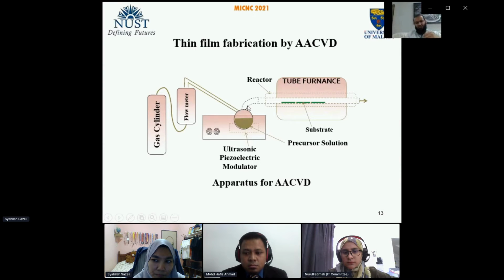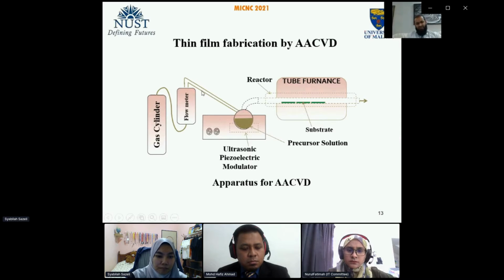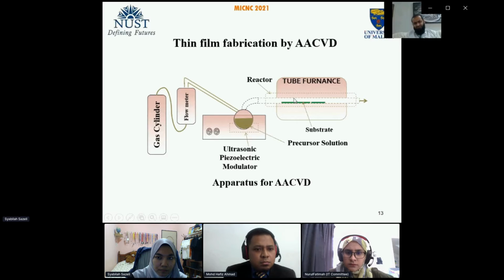The aerosols are produced. These aerosols are pushed by the gas. We are supplying an inert gas like argon, and if we need oxidation of the material, we may use oxygen or air. But in this case, we utilize argon as a carrier gas, which pushes the aerosols into the tube furnace. Once the aerosols have reached the tube furnace, what happens?